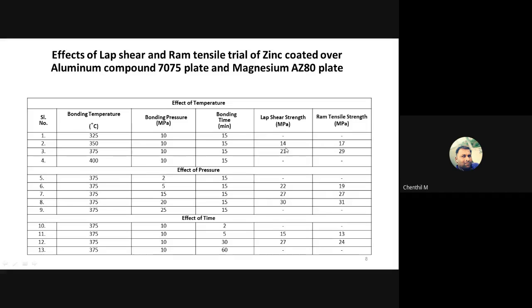As we go on to the effect of pressure, here we are varying the pressure from 2 megapascal to 25 megapascal by keeping a constant temperature of 375 and a bonding time of 15 minutes. Again, for the effect of time, we are varying the time from 2 minutes to 60 minutes by keeping a constant temperature of 375 and pressure of 10 megapascal. From that, we have achieved lap shear strength and ram tensile strength of these amounts.